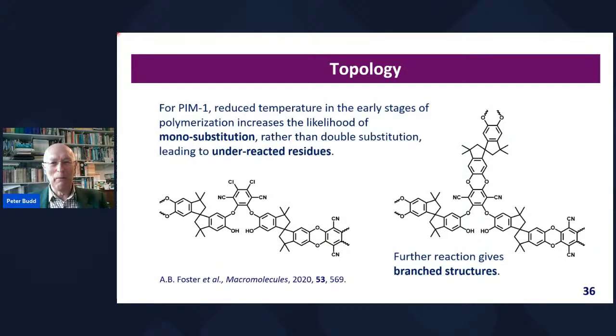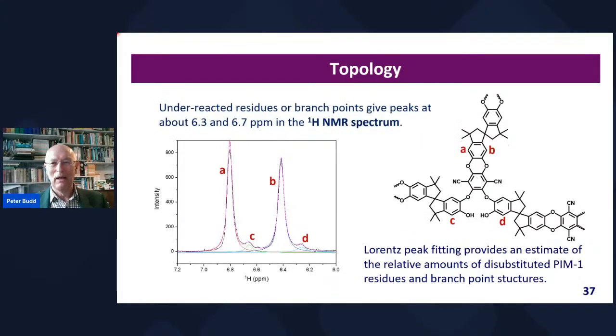And if we think about PIM1, where we're trying to create two bonds at once to create that fused ring structure, if in the early stages of the polymerization the temperature is a little lower, so things go a bit slower, you're more likely to get monosubstitution, which can lead to a defect, which then further reaction gives a branch. Just slight changes in the polymerization conditions can lead to a quite different product because you can get branch structures. And we can tell when you have branch structures in the NMR spectrum, in that you can actually see little peaks which we associate with those defect or branch points and quantify them reasonably through Lorentzian peak fitting.